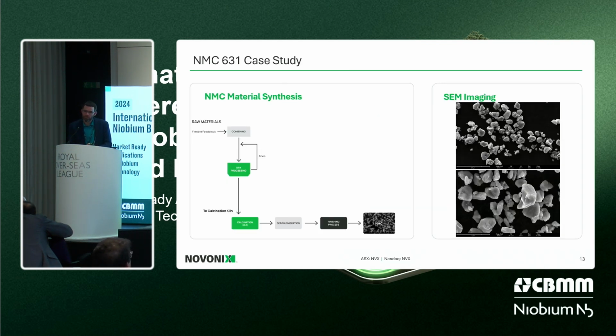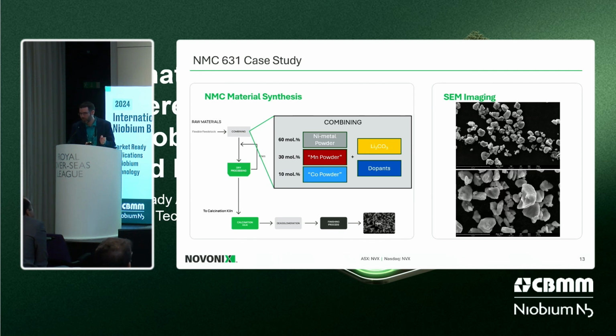So what did we do here? We followed the process flow sheet that I showed in a previous slide to generate NMC by all-dry, combining a few different ingredients. That would be nickel metal powder, a generic manganese powder, and generic cobalt powders in a molar ratio of 60, 30, 10, as one would expect for 631. In a single step, I also combined a melange of dopant materials as well as the lithium source. This is all in a single step. I'm not dosing separately like in the conventional sense. We ran through the all-dry zero-waste process, calcined the material, had some very primitive surface coatings applied to the material, and what you see on the right-hand side is the powder that we get.